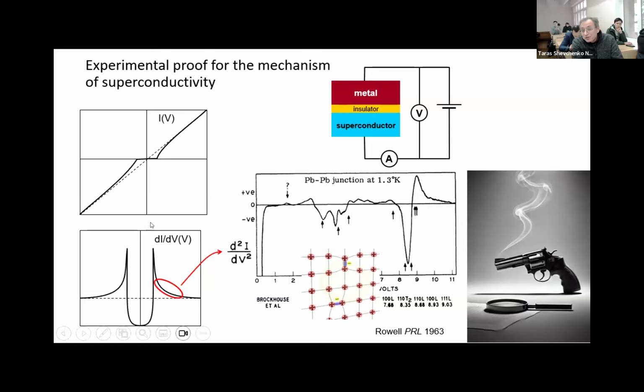Became evident after accurate measuring of its tunneling conductivity. So it is tunneling spectra, a current-voltage characteristic. If you differentiate it, you get some profile which should be proportional to the density of states for the tunnel junction. But if you differentiate it even more, you get some fine structure, and this fine structure should represent the spectrum of, in this case, phonons.